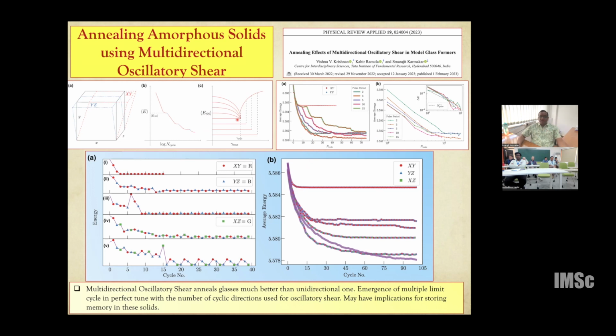This lower bound is a fundamental question which, as I said, nobody has an answer to, and which remains an open question. One interesting thing that we found is that if you do a random sequence of oscillatory shear, then your energy profile goes down, down, down, and it takes an enormously large number of cycles to reach a steady state. This tries to explore various complex paths or minima, and then eventually will saturate at some point because the phase diagram doesn't evolve beyond this.